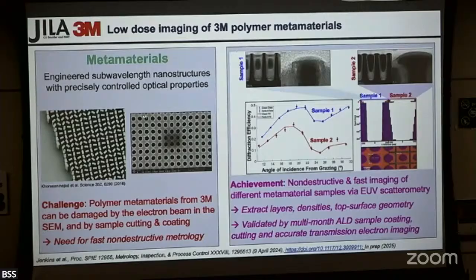And what I forgot to say, the scatterometry is actually very powerful. It can tell you what the layers are, what their density is and what their shape is. That's why you do it as a function of angle, so you can build a model that then has good error bars. Here, it's really just the spot size, so it's 5 microns or something.